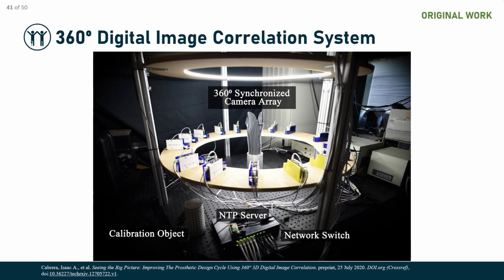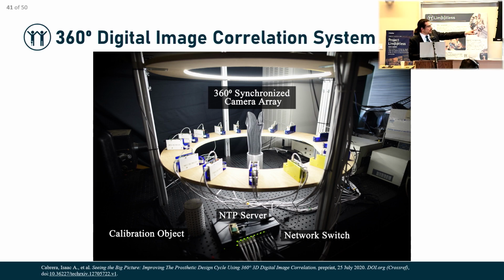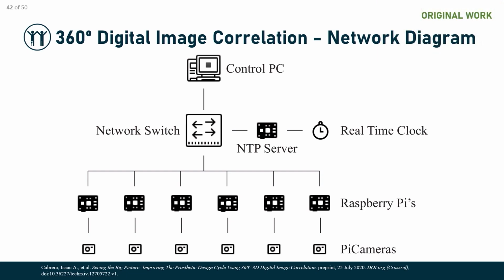It has about 20 cameras around it, and they're all connected together via a network. They're all in a local area network connected via an Ethernet switch. So basically, we're capturing synchronous videos in 360 degrees, which we can use for a technique called digital image correlation. But here's the simplified schematic of that network configuration, where we have a control PC communicating with the network. All those computers are synced with each other with something called the Network Time Protocol. And then we have a master clock that's synchronizing all of the cameras together.